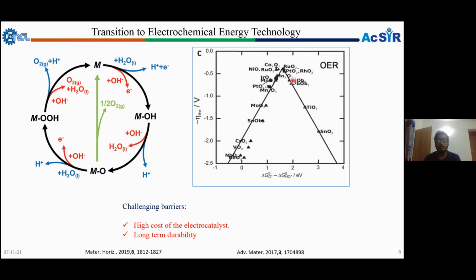The oxygen evolution reaction happens in 1 molar KOH, so at higher pH there are more chances of corrosion of the noble metal. Other reactant species like CO can adsorb on the surface and affect the overall durability of the electrocatalyst, because it has 5d orbitals, which can easily bind CO and other contaminants present in water systems.